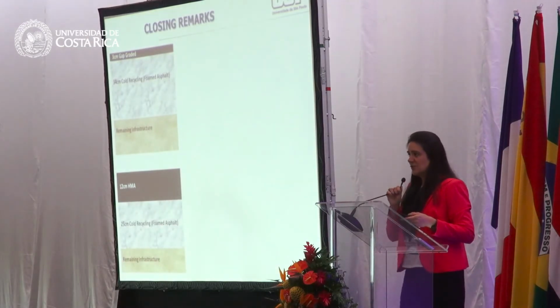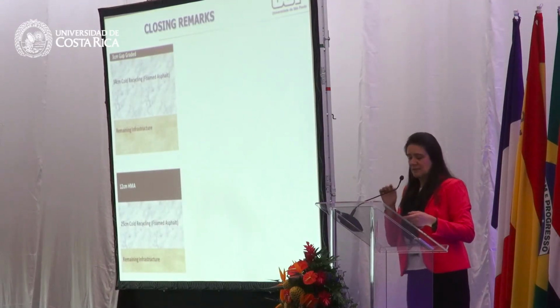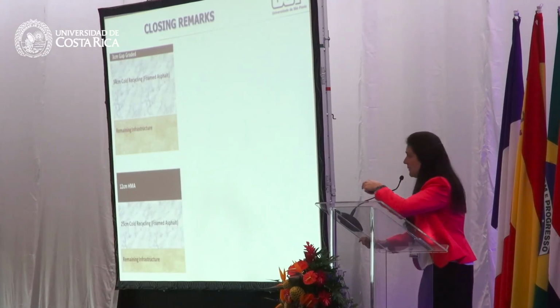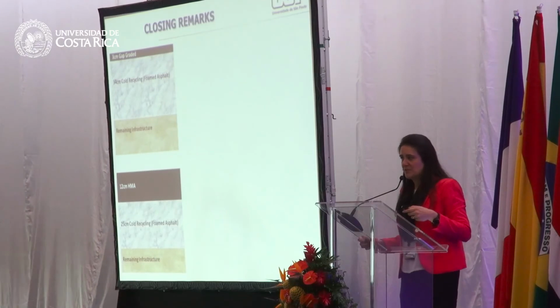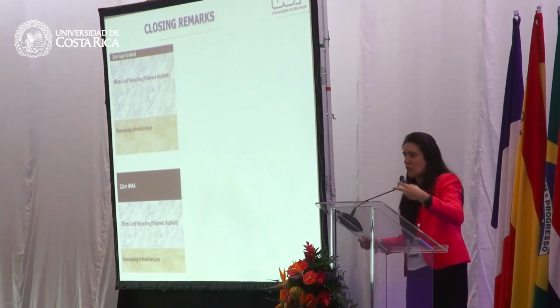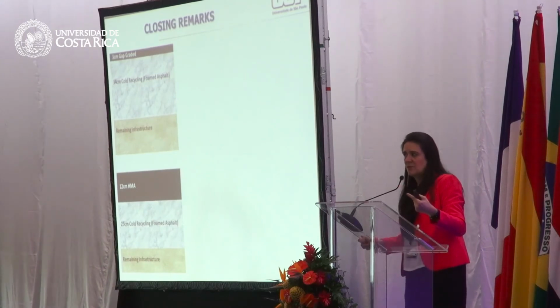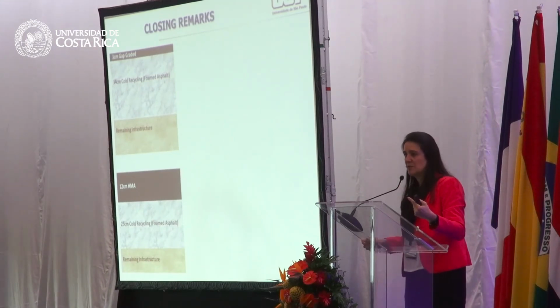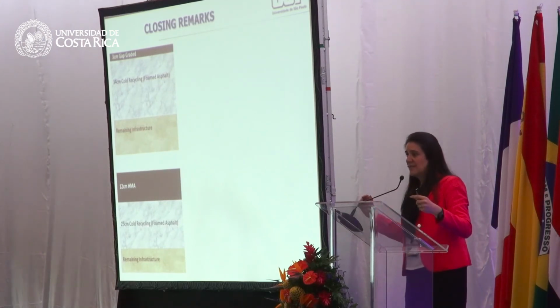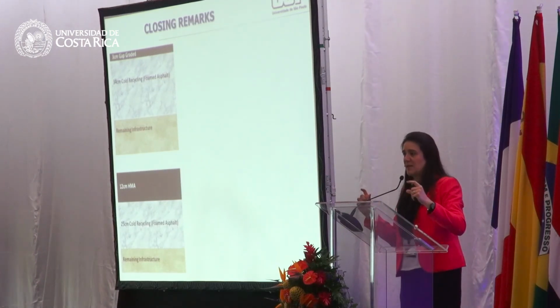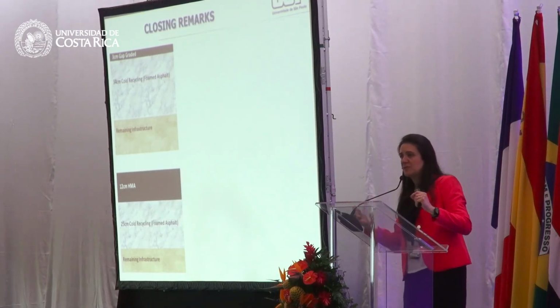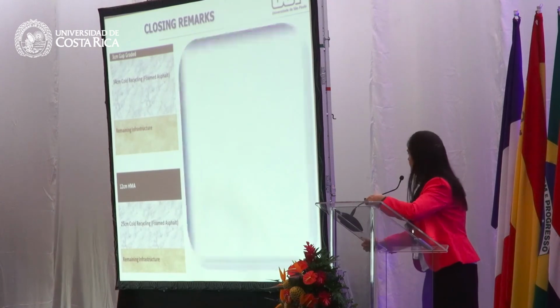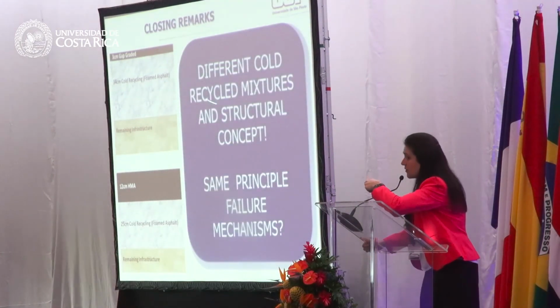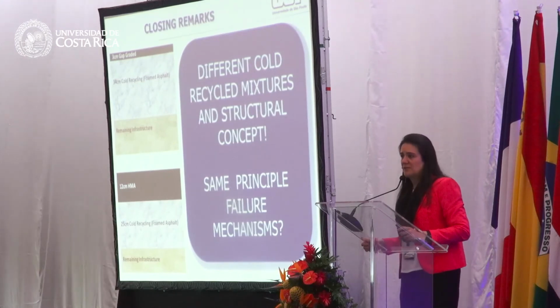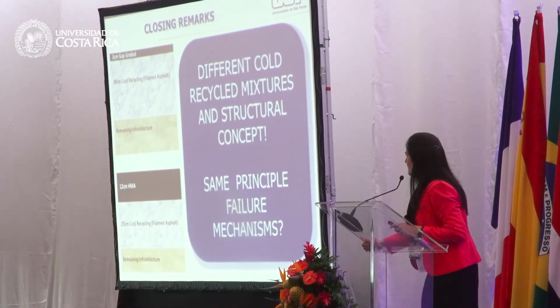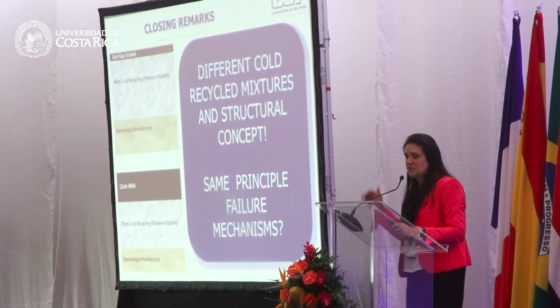These are the two structures I've shown of the two test sites. The first one, I have only 3 centimeters of HMA on top of this mixture. And the cold recycle itself has just 1% of hydrated lime and 1.8% of binder. The second structure has 12 centimeters of HMA, 3% of binder, and 2% of cement. Both are cold recycled mixtures, but they are different. And most probably, the structural concept of these two structures too.